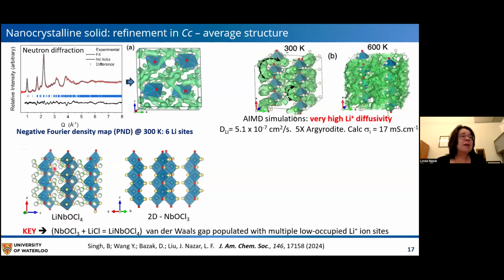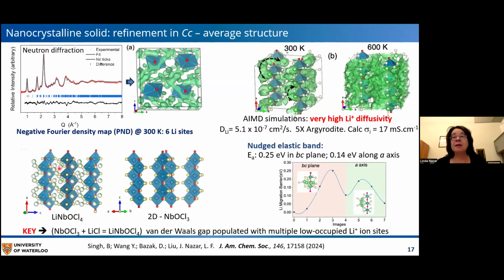And if you look carefully, you can see that there's a very low population of lithium on these sites, and so these sheets are not exactly van der Waals bonded because there is electrostatic interaction of lithium, but it's quite weak because of that low degree of population. So this is key to this material's conductivity, and our NEB calculations show that there's an activation energy of about 0.25 eV in the BC plane, which is this plane, and 0.14 along the A-axis. In other words, in this direction. So this is a very, very low activation energy.